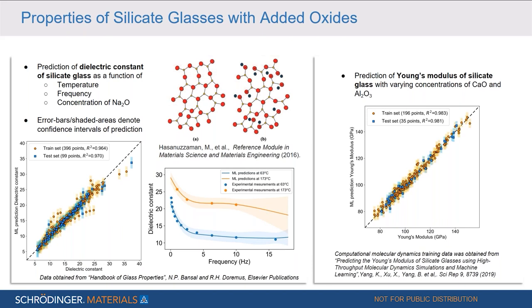The dielectric constant of silicate glasses with added oxides was predicted as a function of temperature, frequency, and sodium oxide concentration. If we take a look at the linear plot, it shows the dielectric constant versus the predicted one. And we see that we have a quite good agreement for both training and test set. So both have an R-square value of greater than 0.9. We can also look at the dielectric constant as a function of the frequency. This is shown here in the middle plot for two different temperatures. The filled circles that we see here are the experimental measurements at the two different temperatures, and the lines are the predictions. And we see that we are in good agreement with experiment.